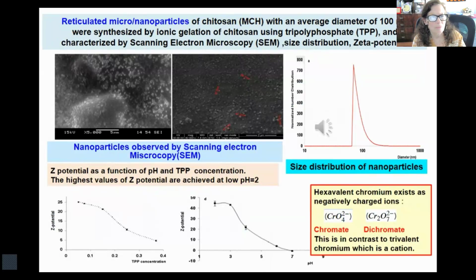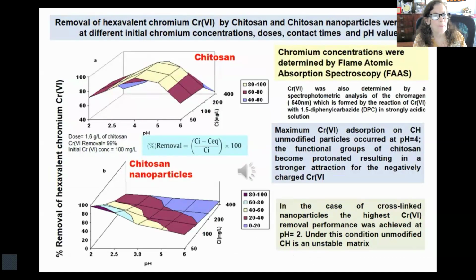The highest values of zeta potential were achieved at low pH. Hexavalent chromium exists as negatively charged ions, chromate and dichromate. This is in contrast to trivalent chromium, which is a cation. Removal of hexavalent chromium by chitosan and chitosan nanoparticles was tested at different initial chromium concentration, doses, contact time, and pH values. Chromium concentrations were determined by flame atomic absorption spectroscopy.